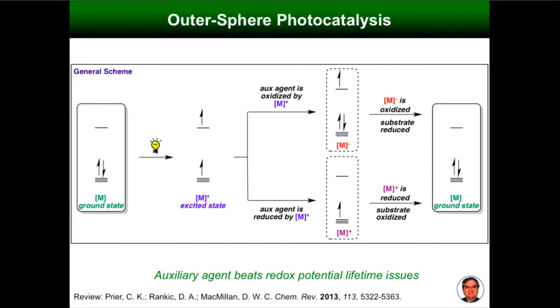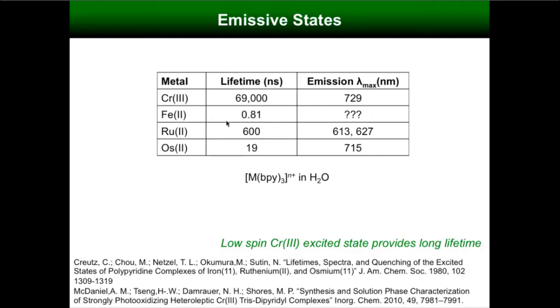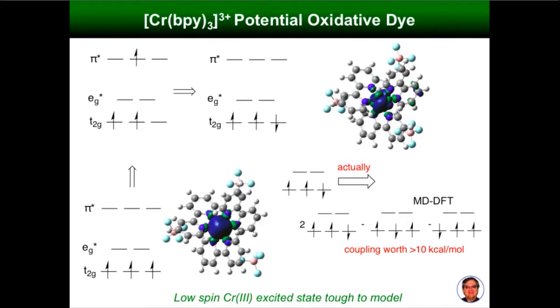This auxiliary agent is there because of the lifetime of the excited state. We're doing chemistry in the excited state. The chemistry has to happen faster than the excited state decay. Ruthenium has a lifetime of roughly 600 nanoseconds for the bipyridyl complex. Chromium, on the other hand, is 69,000, quite a bit longer lifetime. And so can you use chromium instead, exploiting the lifetime of chromium to carry out the chemistry without an auxiliary agent? The excited state of chromium is this spin-flipped excited state, spin forbidden, can't go back to the ground state easily, sticks around a long time.